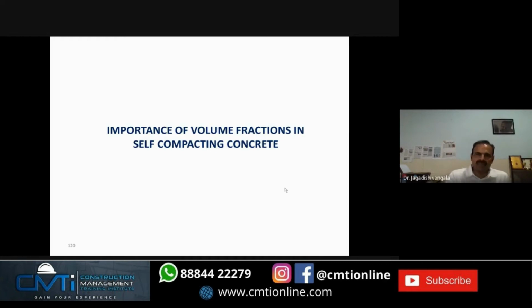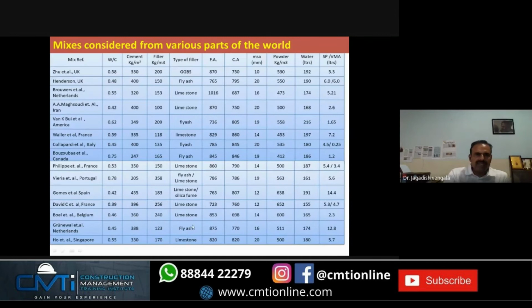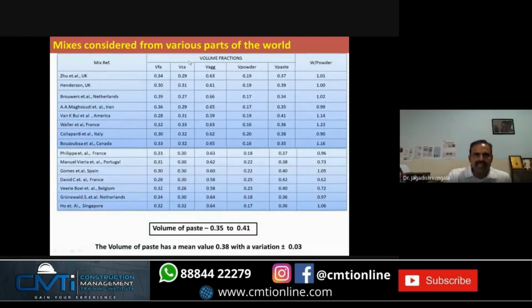Coming to almost the end of my presentation, I would like to give you the importance of volume fractions, particularly in self-compacting concrete. When we considered various mixes of the world, these are the mixes at various places using different fillers. The interesting thing is volume fractions. Volume fraction is particularly paste, how much paste is required to maintain the flowability of the concrete and to maintain homogeneity in the concrete is very, very important. Paste is a combination of cement plus cementitious material plus water. We call it a paste.